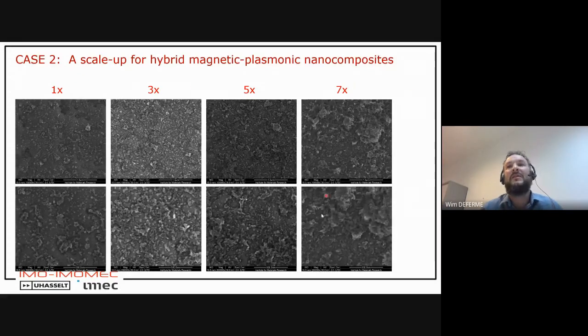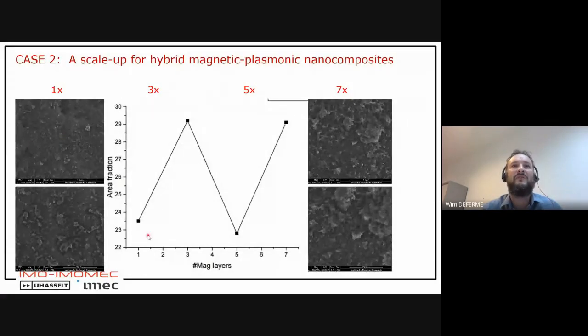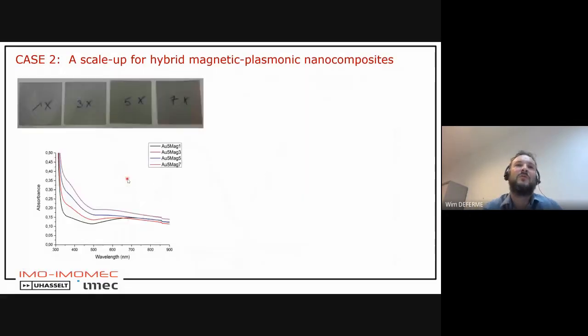on top, then of course your nanoparticles will only stick to the gold, and you will always have the same coverage. And that's what you see here. If we have an area fraction of gold of 25 or 26, we do not change from 1 to even 7 layers. We do not change that much in surface coverage. So this is more or less showing that the silver is only binding to the gold.